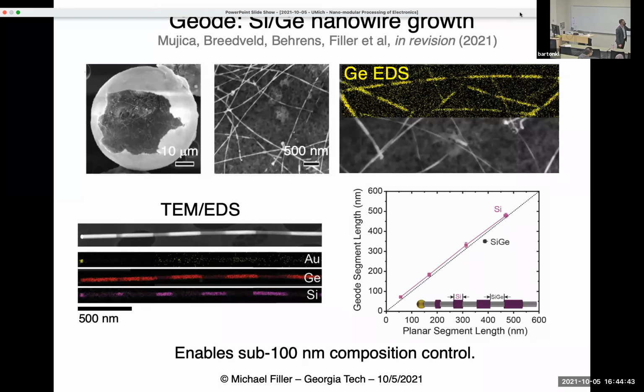We could also program the structure. So it's not enough to just grow a bunch of wires. You have to grow devices, right? So I showed you before, outside of capsules, that we could create these very controlled profiles. This is not silicon and doping. This is silicon and germanium. And we've intentionally encoded these germanium segments in the silicon germanium nanowires.